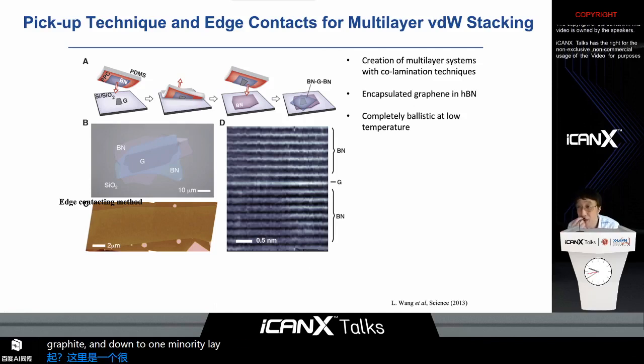And here's a good example. Here we cleave off graphene, a single layer of graphite, down to one monoatomic layer, and we can encapsulate it with boron nitride, which is a graphene-like material but an insulator, and form these atomic stacks out of it.